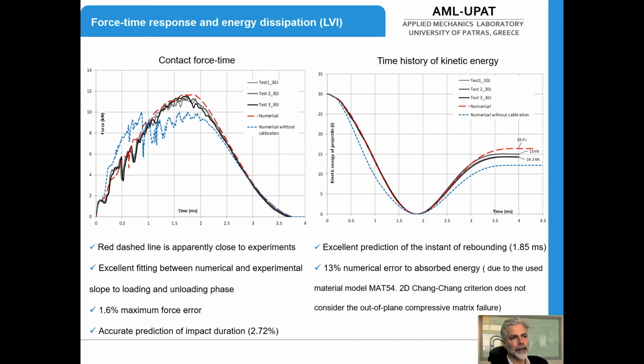Among the things that I would like to stress here is that in the case of the absorbed energy, there is a deviation from experimental data to the calibrated simulation material model of close to 13%. This is not something that we can ignore. However, we are very convinced that this is due to the material model and the failure criteria that we decided to use, because we use the Chang-Chang failure criteria, which does not consider the out-of-plane compressive matrix failure. So, in our opinion, if we use a different material model, this deviation will not be there.